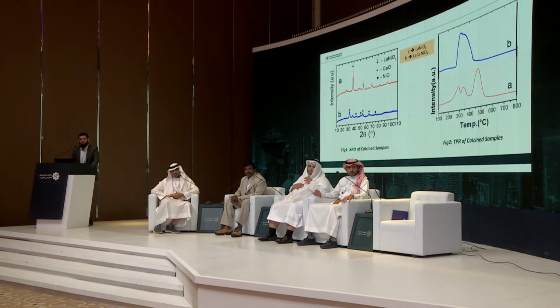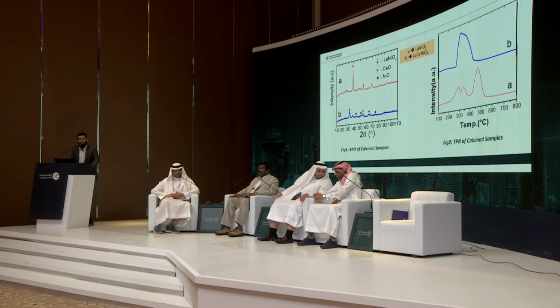Five minutes left, Doctor. At the end, I will discuss some of the physicochemical properties of this lab prepared catalyst. These are the XRD phase structure, and the crystallinity of this lab prepared catalyst was determined by powder XRD. And you can see that when we add some amount of ceria to our main catalyst, there are some additional peaks appearing in the XRD in the left side picture.